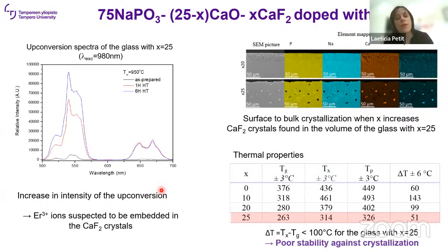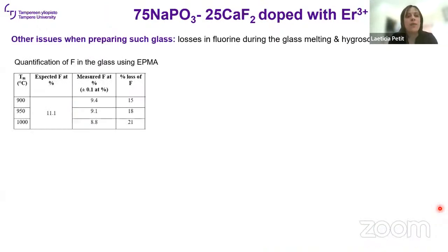However, when we look at the thermal properties of this glass, so this is the one highlighted in red, the delta T, so the difference between the onset of crystallization and the glass transition temperature, is really small, it's only 50. So it's impossible to try to draw the fiber from this glass composition because it has a poor stability against crystallization.